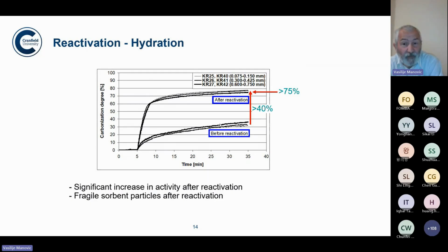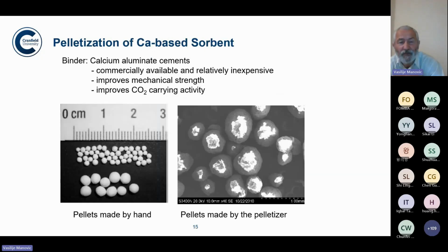So the same samples, when we exposed them to the steam, you see it performed the same, even if not better, than fresh material. So that was one of the main reactivation techniques that we considered. But the main problem, when you reactivate calcium oxide with steam, you will get fragile, fluffy particles that you cannot handle in a fluid bed. It would be elutriated. So we needed something more to do, not only to hydrate and reactivate by hydration.